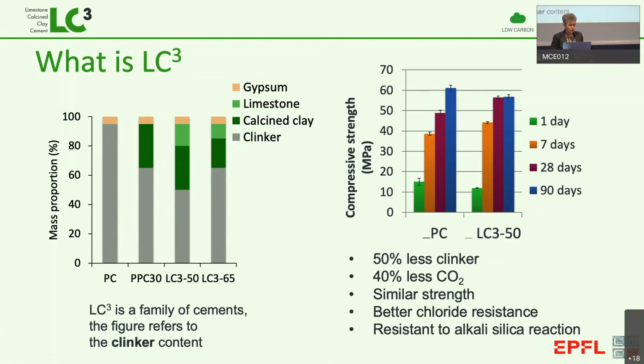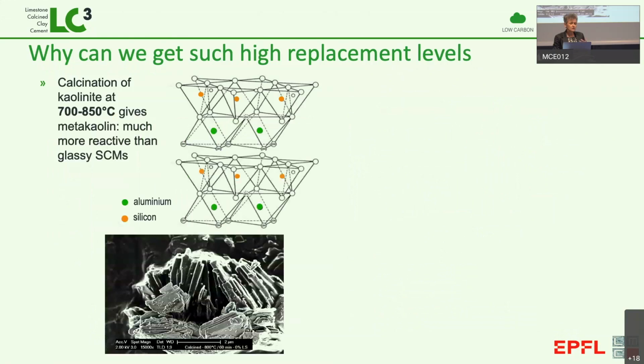This amounts to 40% less CO2 emissions, similar strength, and some properties like, for example, resistance to chloride ions and alkali silica reaction are very much improved. Now, the reason we can get this very good reaction is because of the clay structure. Clay has this layered structure. You can see this is at the atomistic level.